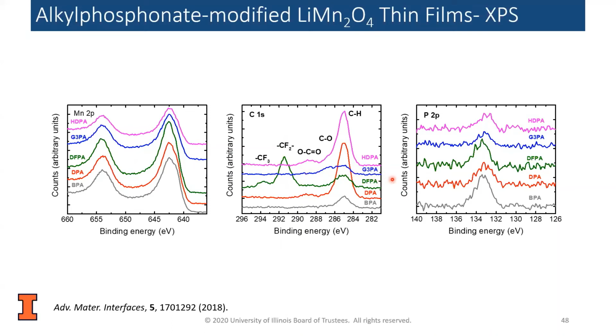And so this signal, because it's so low, indicates that either we didn't get a coating, or if we did get a coating with this SAM, it just fell over. And that would not surprise us, because the polyether has a hydrophilic type chain. It might just tend to fall and stick to the surface of the oxide.